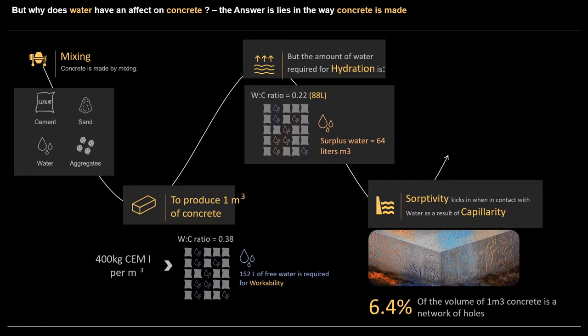During the hydration phase, that excess or free water will leave the concrete, and it will leave in its wake a network of pores and capillaries, which are more or less interconnected throughout the whole concrete matrix. If you crunch the numbers here, you'll find that 6.4% of the volume of this extremely high quality concrete is a network of pores and capillaries. And the thing that a capillary does very well is suck water. It's the basic mechanism by which a tree gets water out of the ground through capillarity.